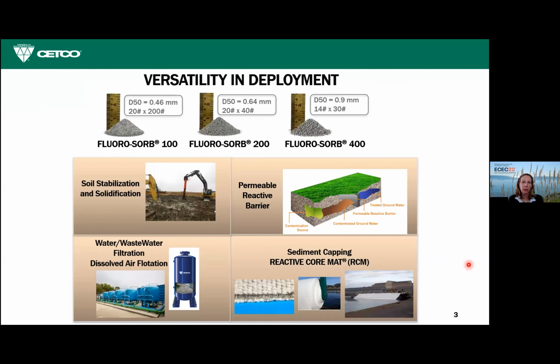To start, Fluorosorb is very versatile in its deployment, and that comes primarily from the ability to manufacture the product in different grain sizes, which are shown here. The D50 that you see listed at the top for each little pile is the median diameter. So the smallest product is Fluorosorb 100, and that is being used for soil stabilization and solidification. So stabilization, if you just want to stabilize PFAS and reduce PFAS leaching in soils, and solidification, it can be mixed with Portland cement. I'll show some results if I have time. It's my very last slide.